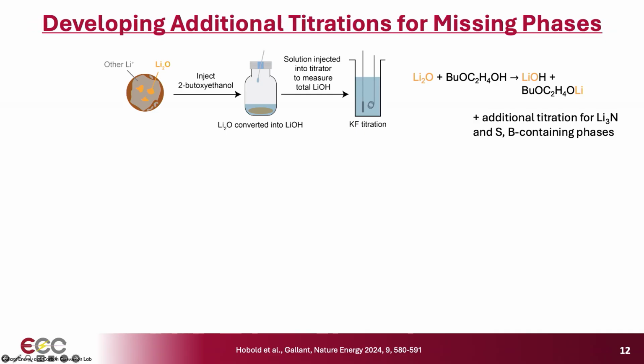So with some trial and error, we landed on the following reaction. You can react lithium oxide with butoxyethanol. It will convert the lithium oxide to lithium hydroxide, and then you can quantify how much lithium hydroxide is in your sample using Karl Fischer titration, which we do in our lab. We also expanded the titration toolkit, so there were a few additional ones we added in this particular study, including one for lithium nitride. I'll spend a little less time focusing on that.